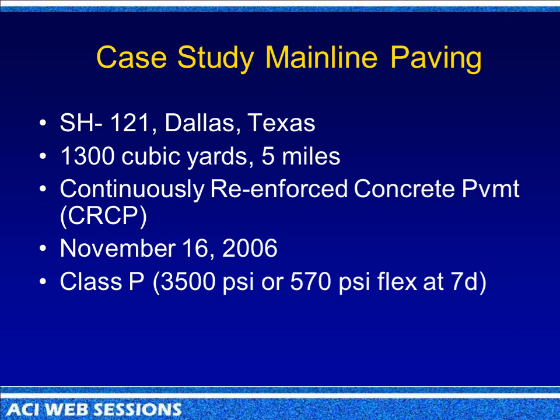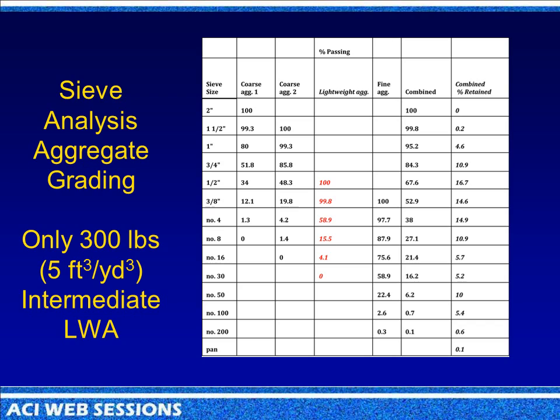Now here's some case studies, Mainline Paving out of Texas. This is 5 miles, continuous reinforced concrete. They did it in November 2006. And here's their strengths at 7 days. Why I point this out is they're only putting in 5 cubic feet, about 300 pounds, and it's an intermediate grade. It goes from about 3/8, 100% passing to 3/8, down to just only 4% passing to number 16.